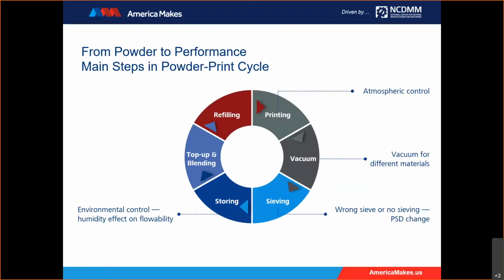If we think about the main steps in the powder print cycle, we can see all the factors that affect our printing of the powder in this wheel. So while printing, we have to ensure good atmospheric control to prevent oxygen or nitrogen pickup, which could be detrimental to the mechanical properties of the part. We often recycle our powder to reduce costs, since most of the powder isn't used to make the part. And that requires us to vacuum the powder from the printer after the build and sieve out any spatter to get our desired particle size distribution.